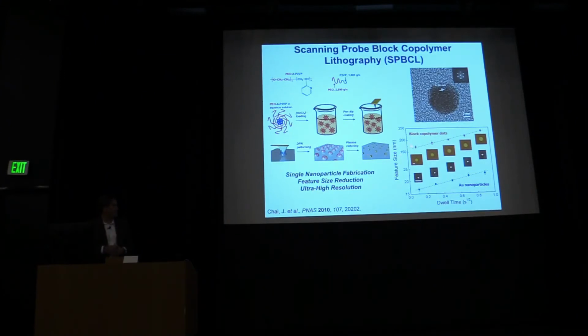And here you can see that's exactly what happens in the case of gold. I generate, in this case, reactors that vary in size, in diameter, from 160 nanometers up to about 220 nanometers. Down here, the particles that I get, one particle per reactor, is a single crystal of gold. And you can see roughly 17 nanometers up to about 22 nanometers. So roughly about a tenth the size of the reactor. Everything you put in a reactor goes into the particle. That's kind of an interesting observation.